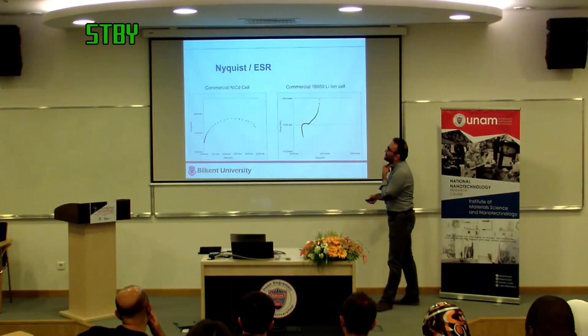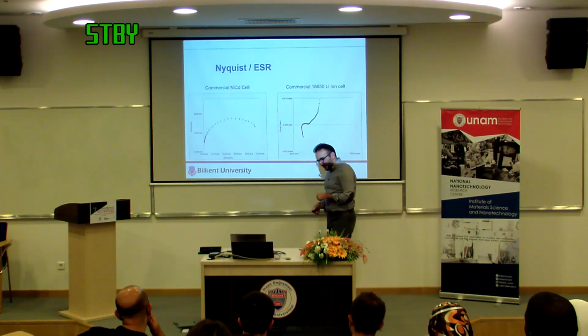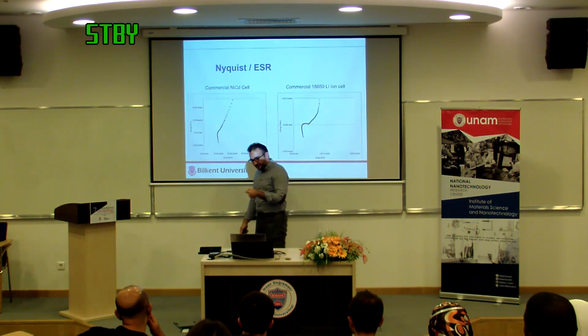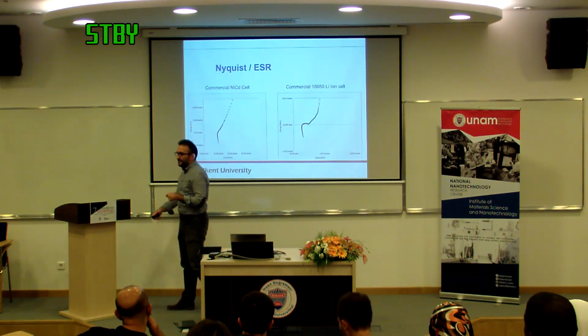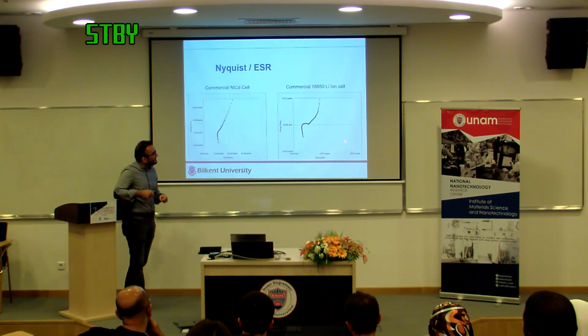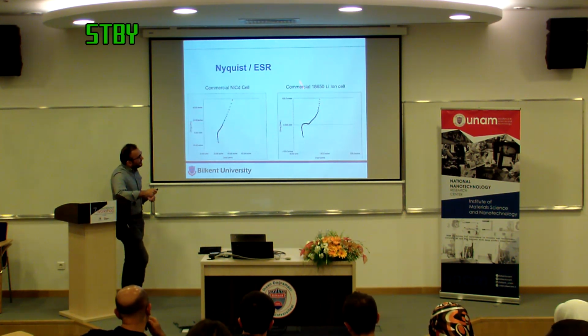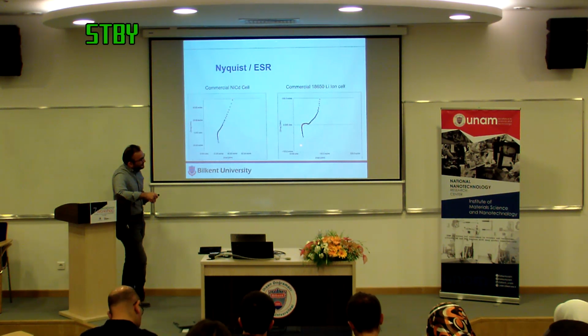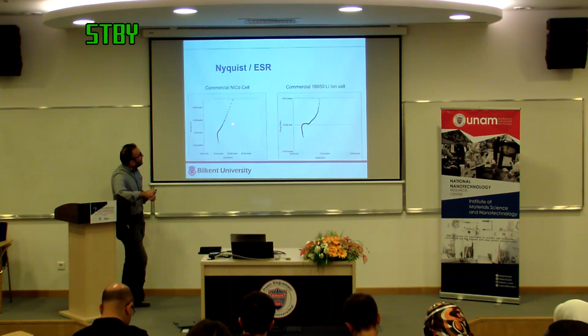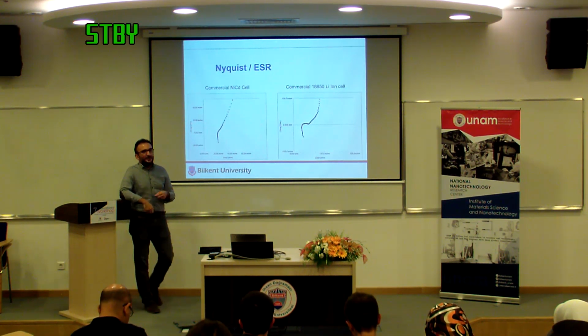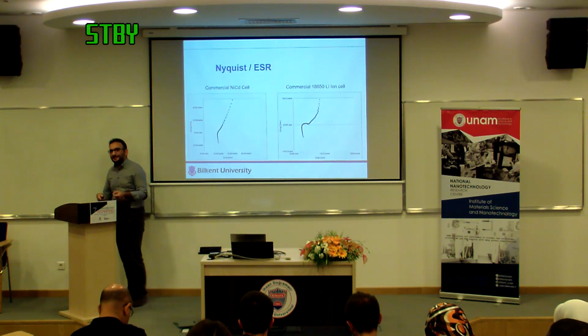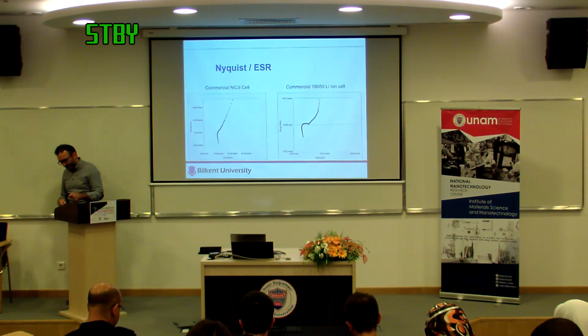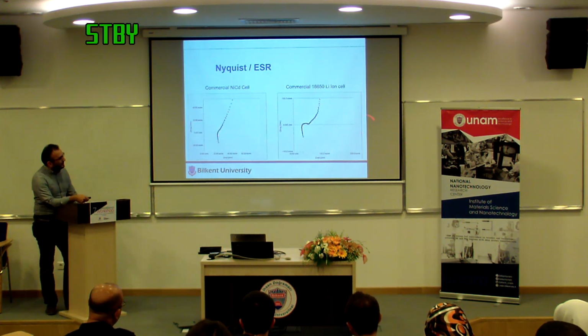So that actually is the easiest number to obtain. All you need to do is look at the high frequency intercept with the real axis. So for the lithium-ion cell, it's right here, about 30 milliohm. For the NiCad, it's about here, so about 25 milliohm. That number, you don't even have to do any fitting to extract. You can just look at the data and grab it. That's how you do it on the Nyquist.